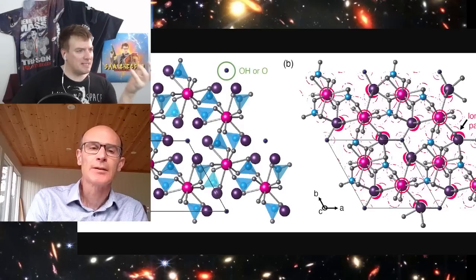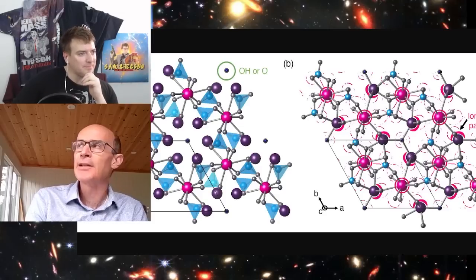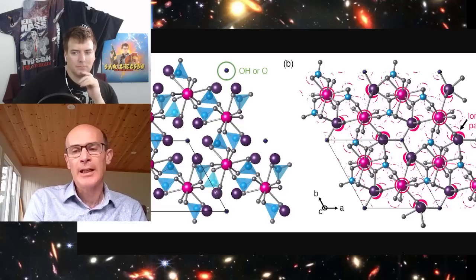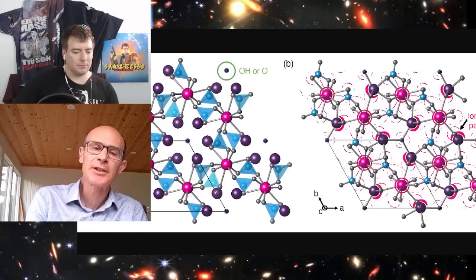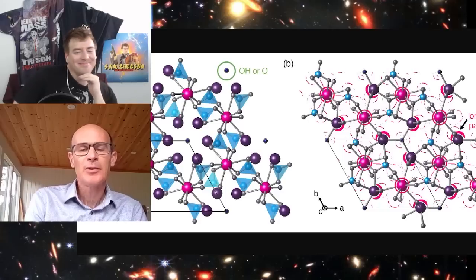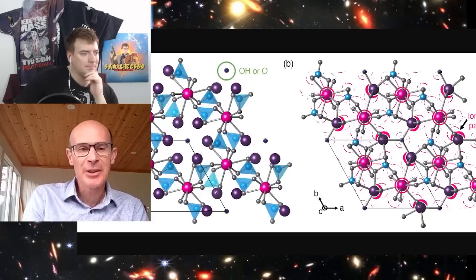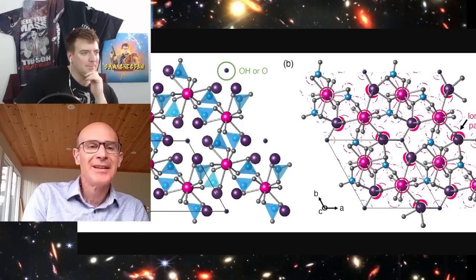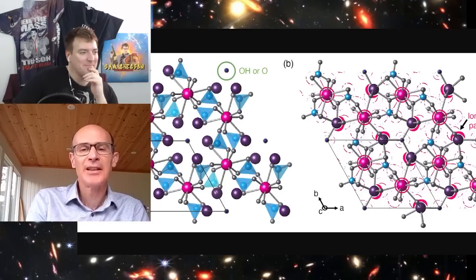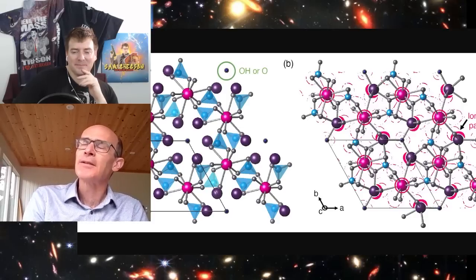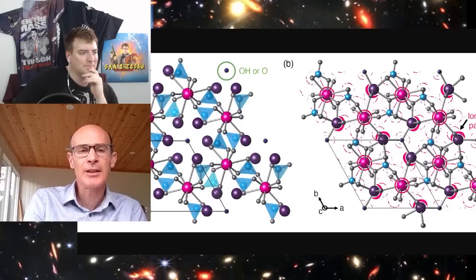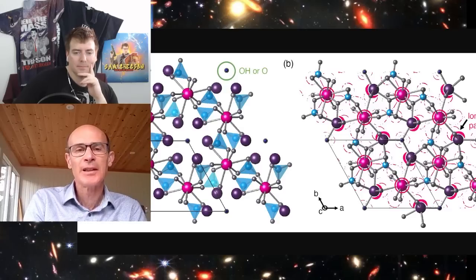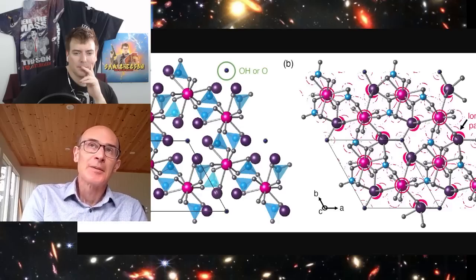But the higher level idea is that you need to know exactly what you've got to be able to understand what you've got. You certainly need to make, in my view, pure material where you know the composition, you know the crystal structure, and then you can measure the properties. So measuring electrical resistance in a multi-phase sample, you don't really know what you're measuring. That's a big challenge. Any measurement where you have to attach electrodes to your sample relies on you knowing what's between those two electrodes, for a start. That's one of my concerns about this field, that there doesn't seem to have been any attempt that I can see yet to make single phase copper substituted lead apatite. So that's still to be investigated.